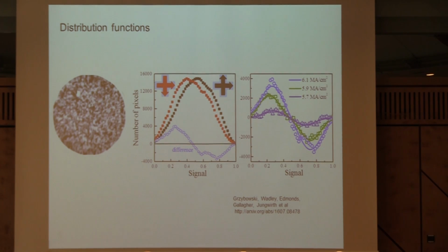If we take these 16 back and forth images and statistically analyze the two sets, up and down, one can see, in this histogram of the distribution of intensities, where these large differences are happening. One can also correlate this difference to the applied current, and it correlates perfectly.